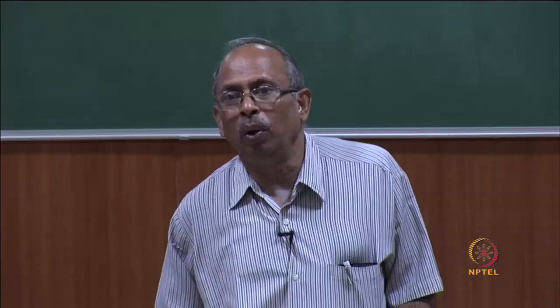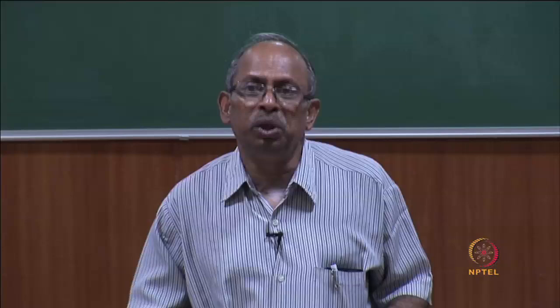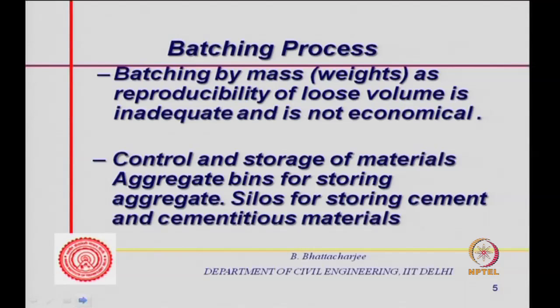So, engineered concrete is produced on mass basis, and that is what your Indian standard code IS 456:2000 also says. Because on a mass basis you can reproduce it, loose volume cannot be reproduced, and it is not economical, except for some small job, you would not do it.